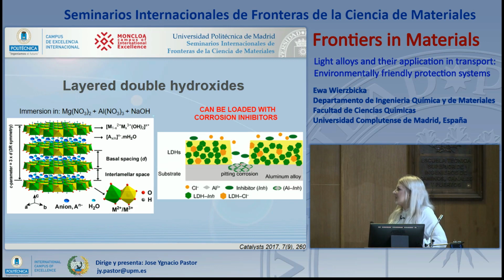Very novel is the application of layered double hydroxide as a conversion coating. It is composed of a layer of 2+ and 3+ hydroxide and a layer of anion mixture with water. This structure is so interesting because it can be loaded with corrosion inhibitors, and then in the presence of corrosive media, there is an exchange reaction in which the LDH bonds the chloride anion, and the inhibitor is released and can be precipitated in the place of coating damage.